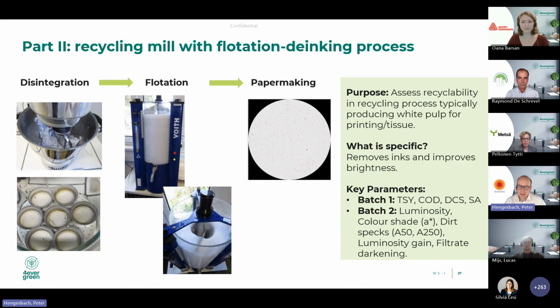And what you can see on the right side is an outcome. In this example, you can see some dark spots. Of course, this is not an ideal outcome, but this is something you might also observe with certain inks or certain additives that have been used for the converting process, potentially causing issues in the quality, and this is what we are investigating with this evaluation protocol. The end use of those products covers quite a range. It can be printing graphic paper, but also tissues. And the removal of the ink, as said, is the very specific thing highlighted here for this process, which is different compared to the conventional process.